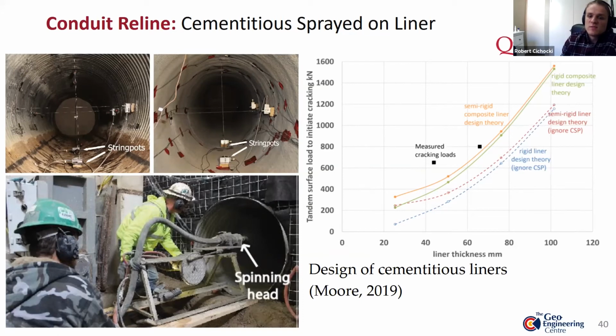Following a similar set of experiments that I previously talked about, where we looked at Ontario truckloads on the shallowest culverts, we saw that this rehabilitation method did significantly stiffen the system. Further, we saw that it behaves as either a rigid or a semi-rigid pipe. And we were also able to propose a variety of design equations for this method using either composite or non-composite action.